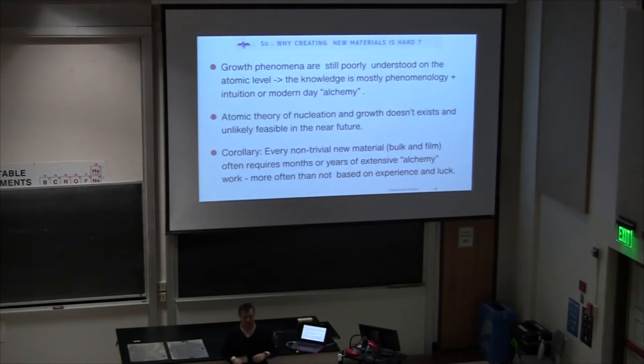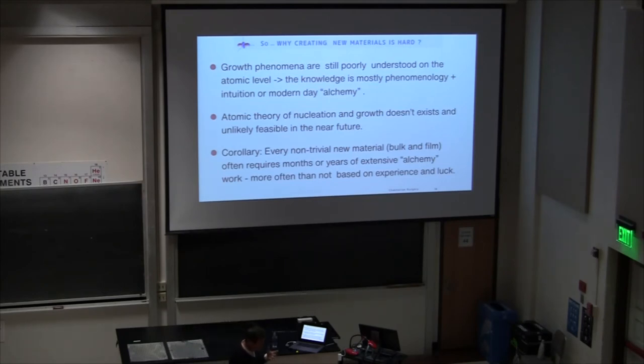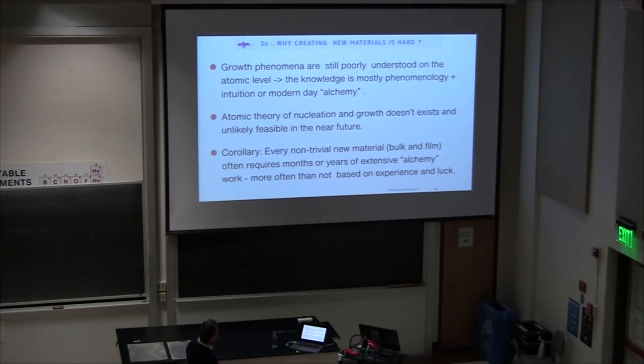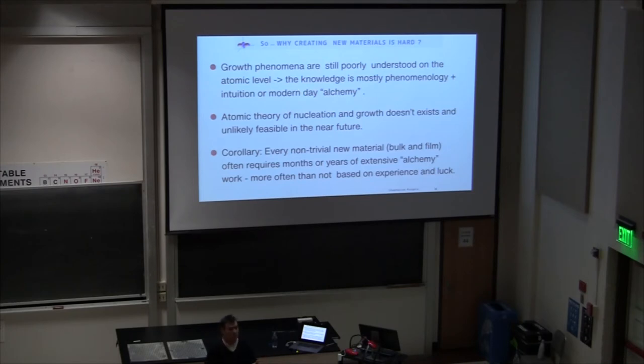Why aren't we producing a fantastic new material every three days, if we know what to do? Here's my answer — it's personal, my colleagues may disagree. Creating new materials is so hard because growth phenomena are still poorly understood on the atomic scale. You can try DFT, but DFT is T equals zero; you need more powerful methods like Monte Carlo, which are computationally very expensive. So what we know is mostly phenomenology — a lot of intuition and experience goes into growth, and I call this modern-day alchemy.